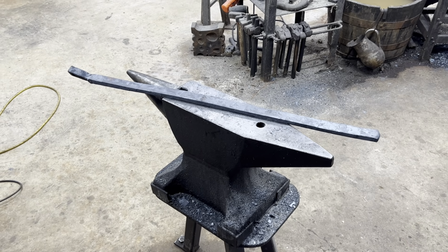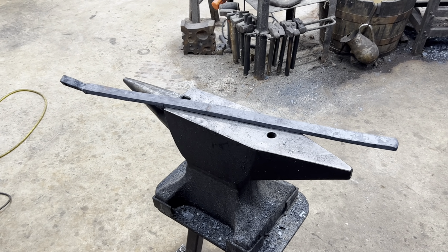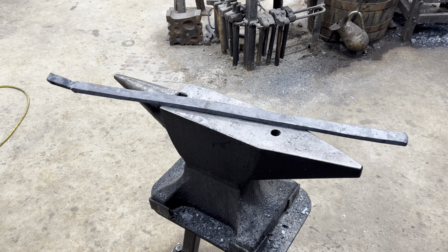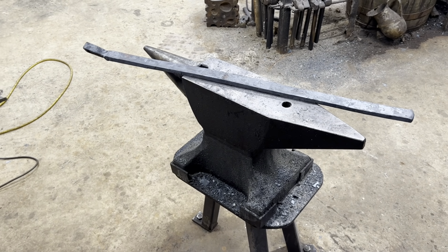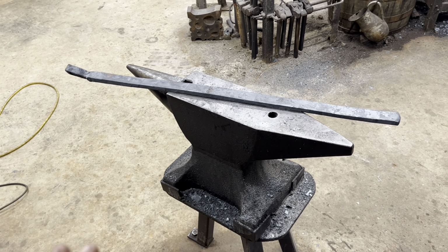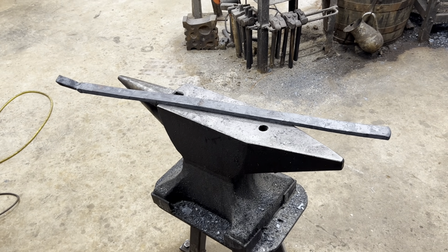Alright, so all the forge welding took a couple of days, but here we got a billet that is approximately 1,000 layers of pattern welded steel. We got about 34 inches of length, it's 1 3/8 inches wide and about 3/8 of an inch thick. And the next step is to go ahead and press in the pattern to make the ladder Damascus.